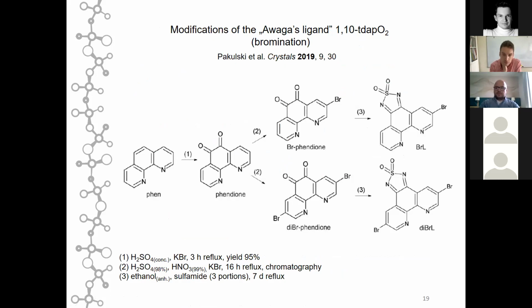So apart from 4,7-phenanthroline dioxothiadiazole, we are also working on functionalizing the 1,10-phenanthroline backbone of this compound. And the first step to do this is the bromination of the phenanthroline, which is not really easy. As some of you may know, phenanthroline is not really prone to any modifications. It's very inert when it comes to substitutions, but you can actually oxidize it to the phendione, which then can be brominated in the 3 and 8 positions. And after column purification, you obtain both compounds.